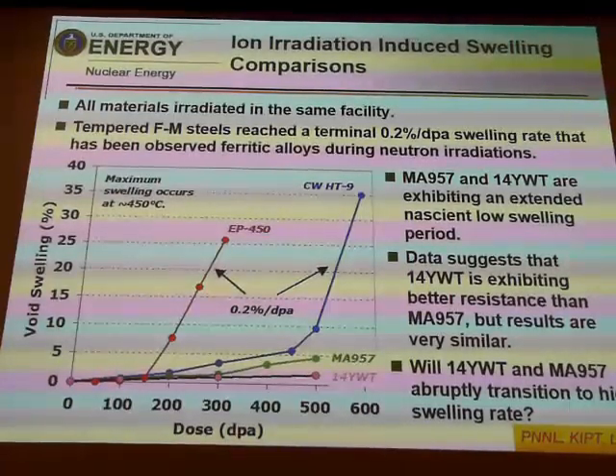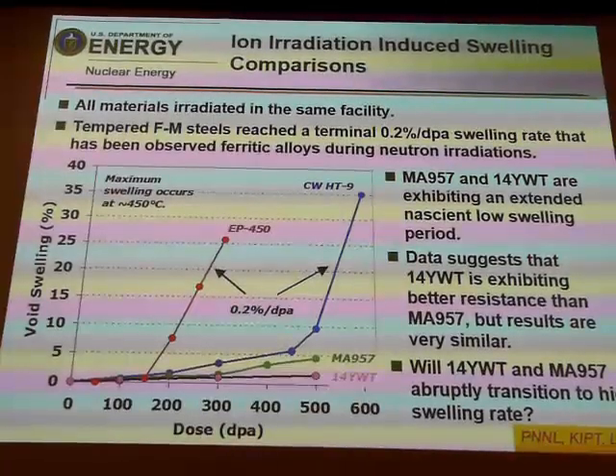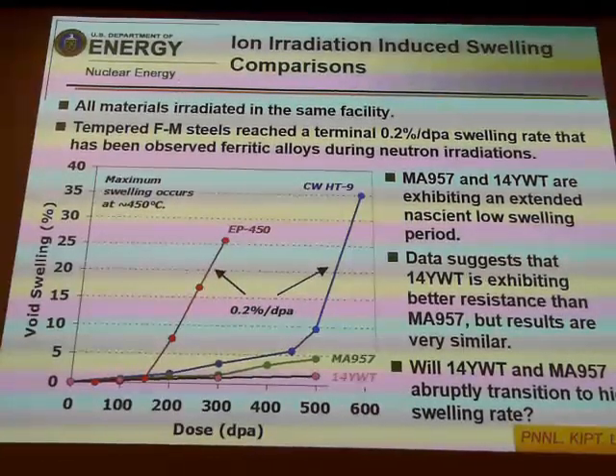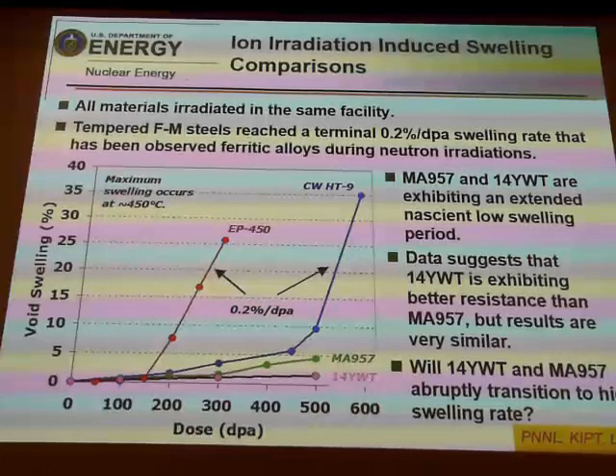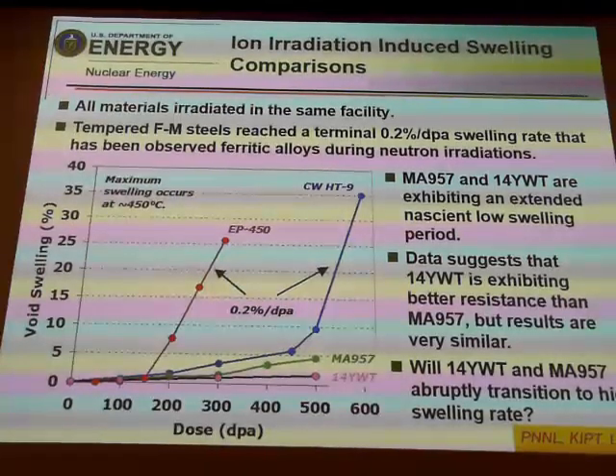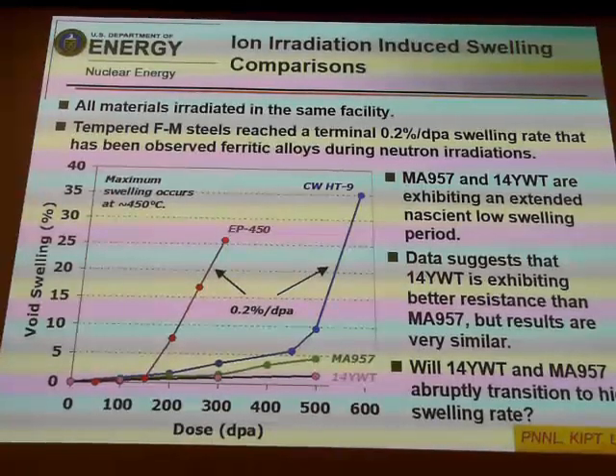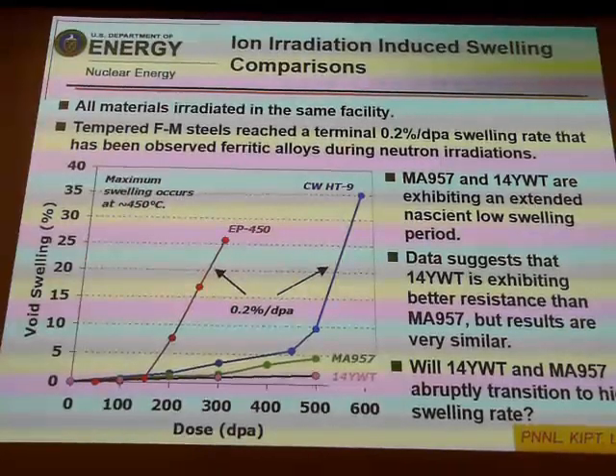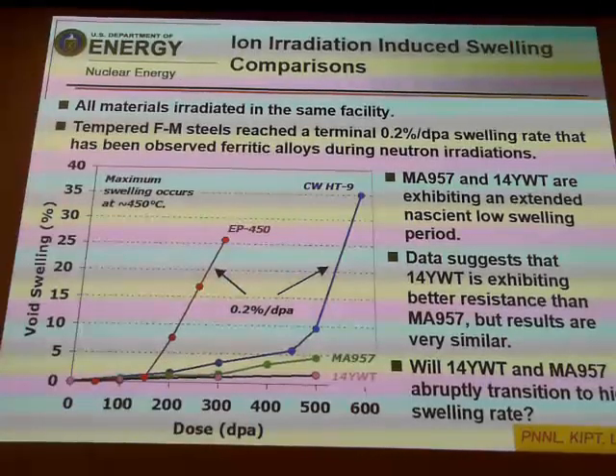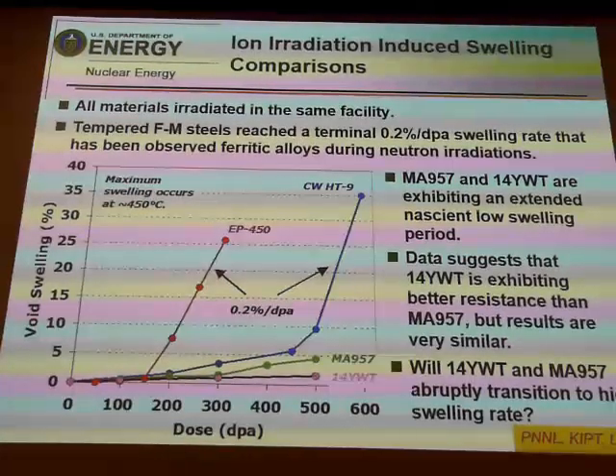In a ferritic stainless steel, which has a more open crystal structure, it takes longer to nucleate voids. So you don't nucleate voids in a ferritic steel like HT9 until over 200 dpa, as you see here. And once you've nucleated them, they start to grow in what we call the steady state swelling regime. It's only swelling at 0.2% per dpa. So it's still a lot.